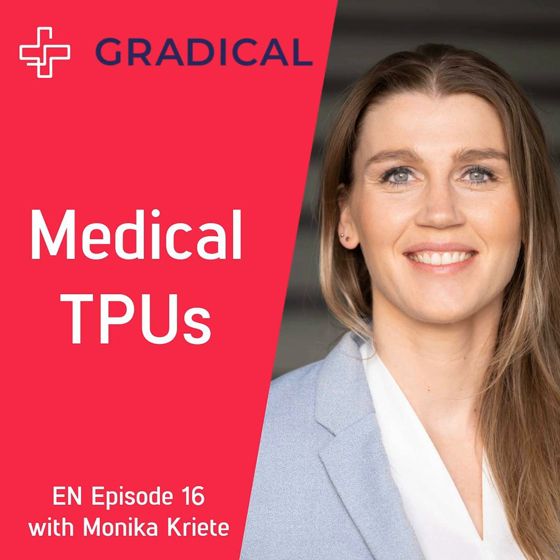In that process, also looking at aromatic TPUs, there can be some volatile substances coming out which you do not want, and it can lead to a lot of fluctuation in your process. This is why we recommend for aromatic type TPUs a residual moisture of 0.02 before melt processing, and for aliphatic type 0.05. And we have a whole guide on the right drying equipment. A desiccant dryer is something which usually works best. It's a hygroscopic material which will take up moisture very quickly. And it's really important to dry it and then also keep it dry before melt processing it.